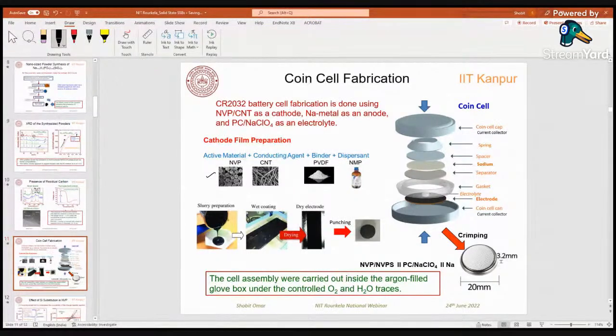Slurry preparation was done, and then we cast this slurry over the aluminum foil and vacuum dried it, and then punched the cathode from this coating.